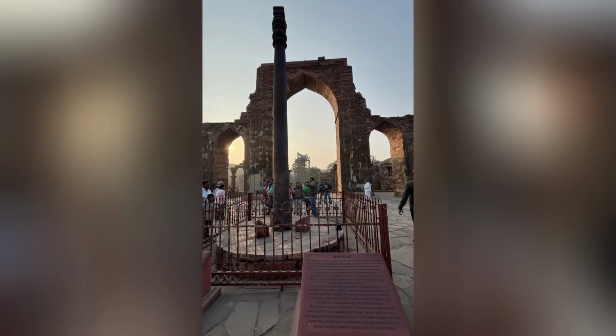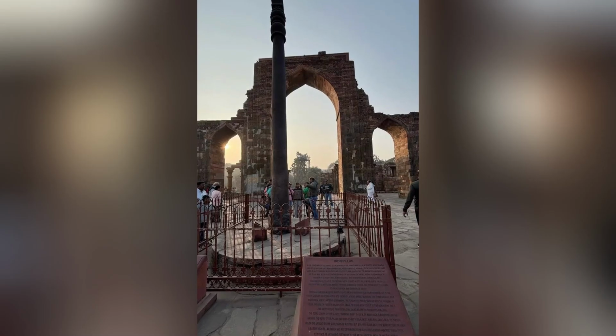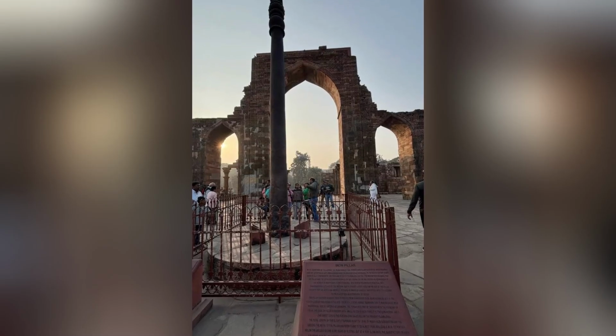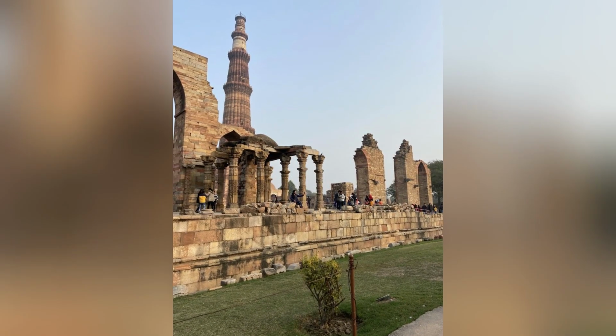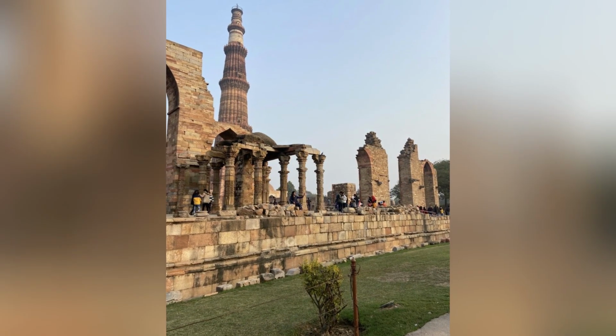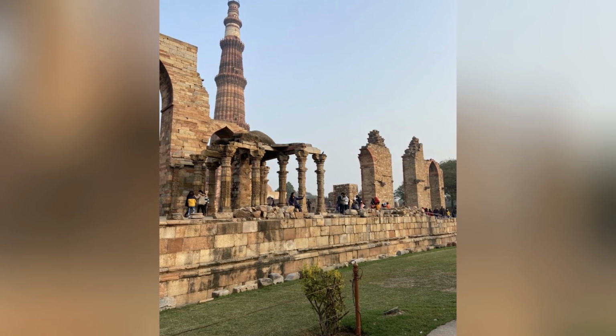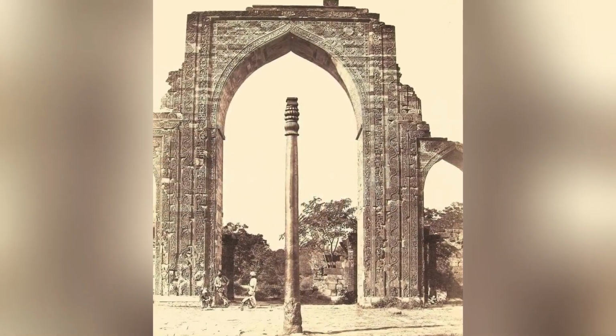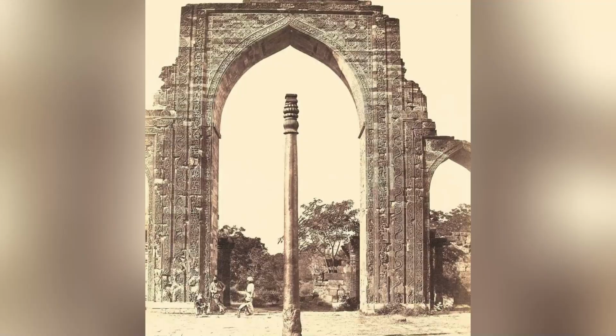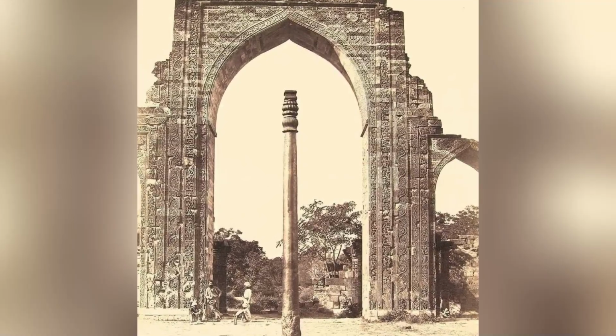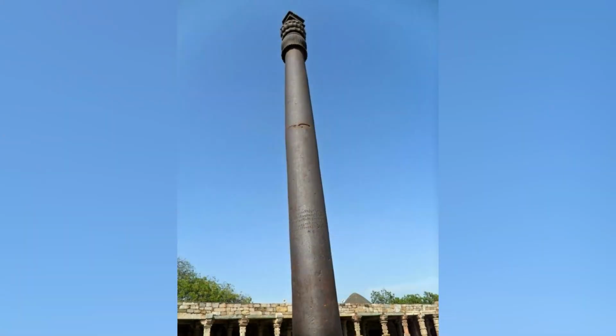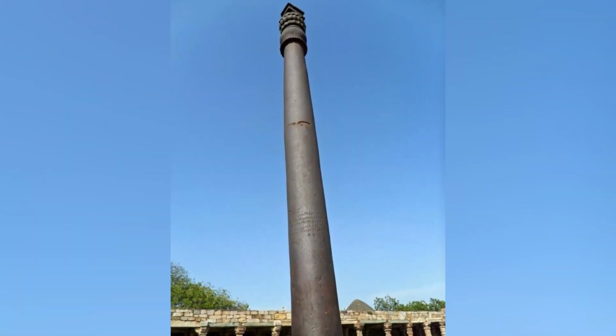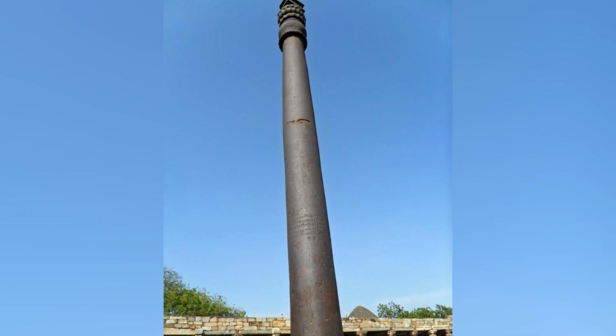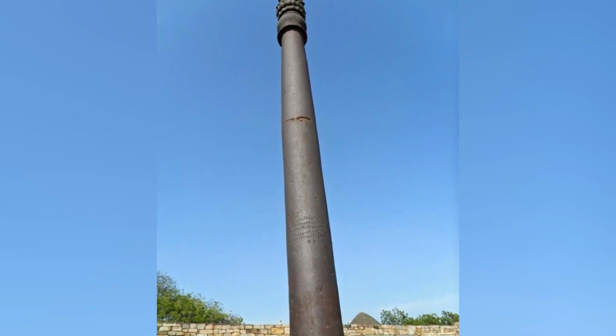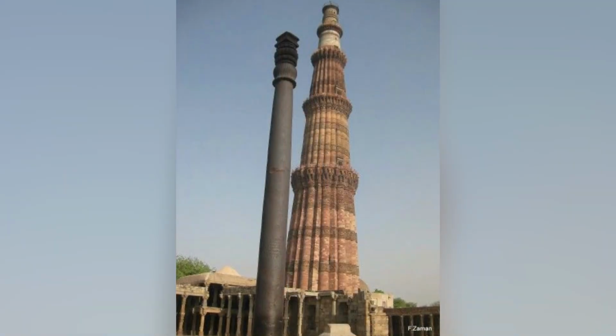The pillar demonstrates that the most effective corrosion protection is provided by a dense, adherent, self-healing film that forms spontaneously on the surface of the metal through the interaction of specific chemical components within the metal with the specific chemical conditions of the environment. The pillar also demonstrates that the formation of such a film is a slow process that requires centuries to reach its full protective capability, a timescale that is far longer than the timescales that are typically considered in the design of modern corrosion protection systems.